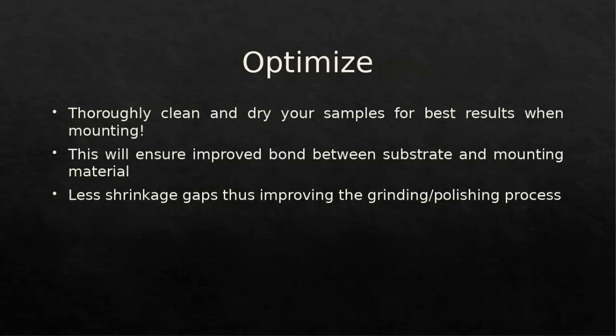So how do you optimize when you mount? After sectioning, when you take that sample out, you're still going to have cutting fluids, everybody's fingerprints, anything like that on the sample. So the best way to optimize your mount is to thoroughly clean and dry that sample. The reason is it's going to help increase the bond between the substrate, being your metal sample, and your mounting material. If you have oils and residues, you don't get a good bond. It's going to repel whatever your mounting media is, creating larger shrinkage gaps. So with a thoroughly clean and dry sample, you can reduce the shrinkage gaps, therefore improving the whole process going through the metallographic steps.